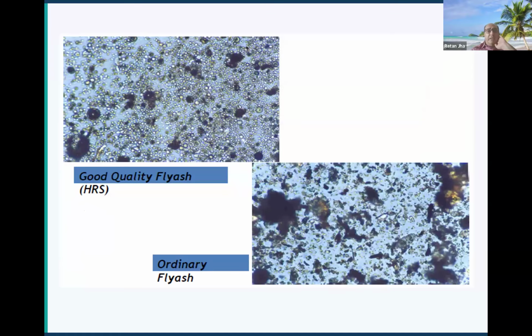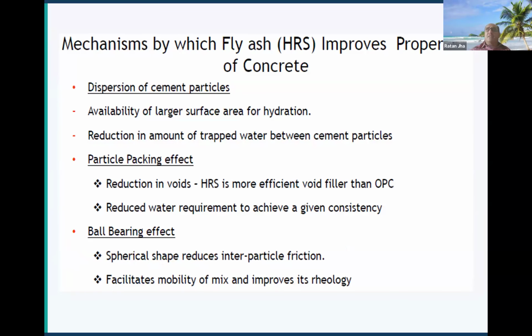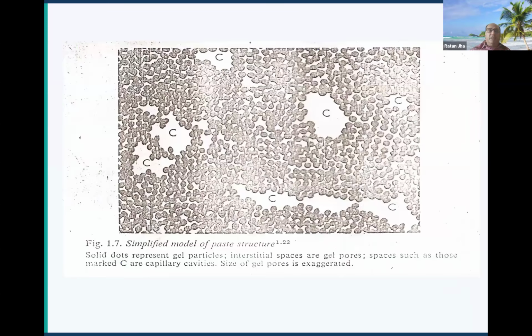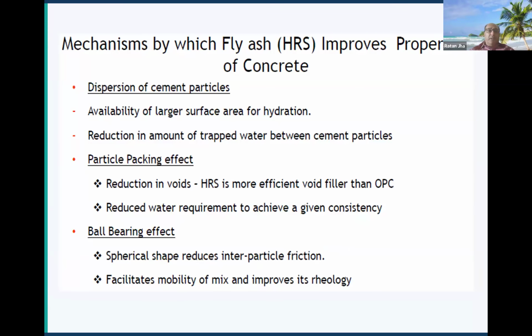All the black particles, black dots, are CSH gel. In case of Portland Pozzolana cement, these particles are less in quantity, hence your concrete will become denser, permeability of concrete is lesser, and as a result the strength and durability increase significantly. Usage of high quality fly ash with highly reactive silica. SEM images of normal fly ash. How does fly ash increase the properties of concrete? First of all, dispersion of cement particles and availability of larger surface area for hydration, because the fineness of fly ash is much larger. Reduction in the amount of trapped water between cement particles. Particle packing effect, reduction in voids. If more CSH gel forms between these two particles, voids will reduce and your concrete will become denser.